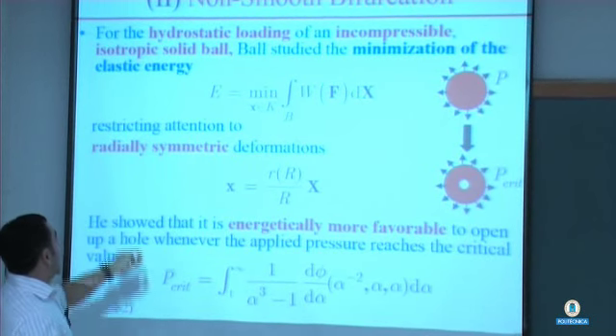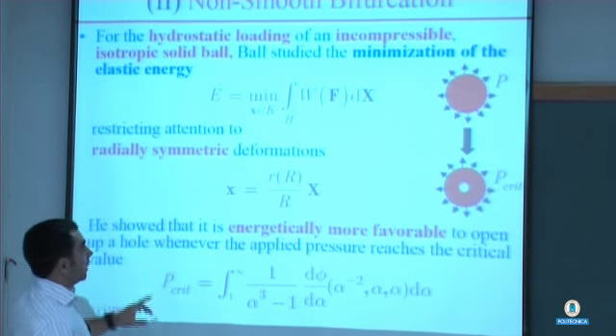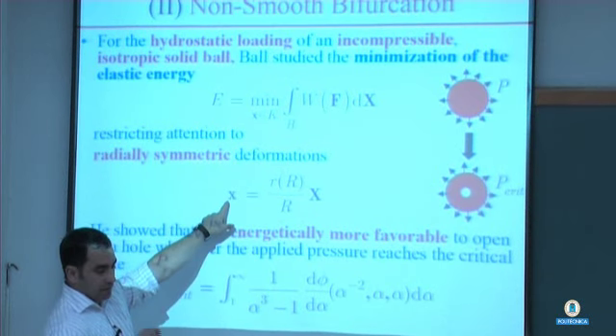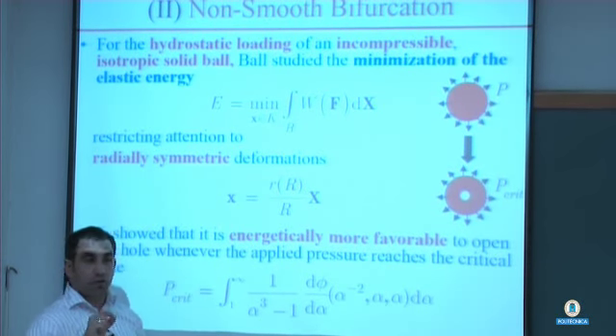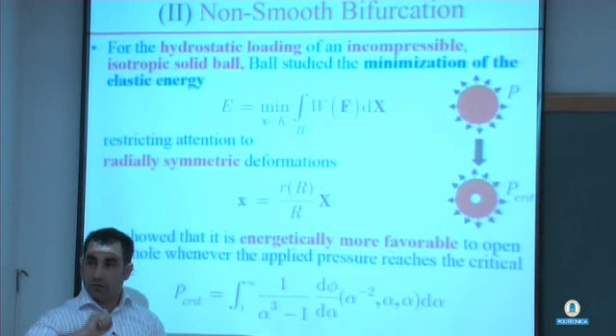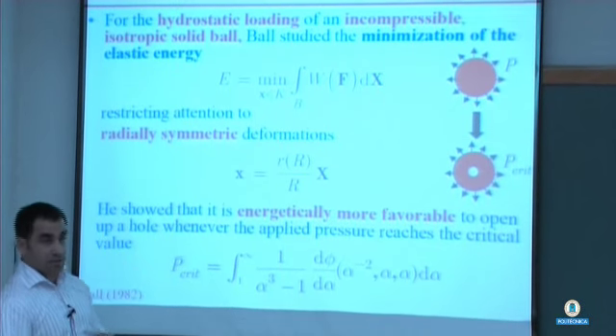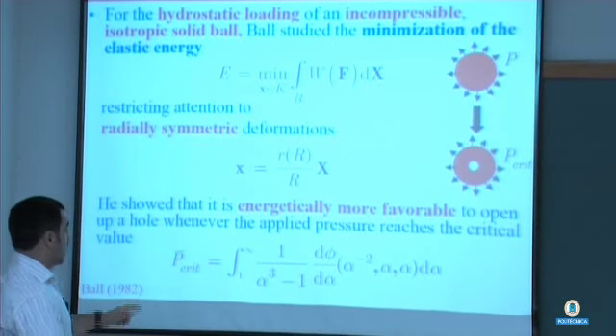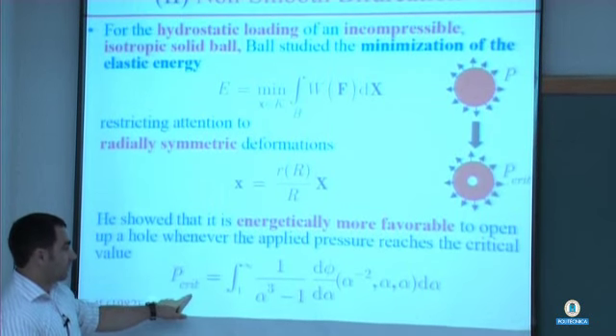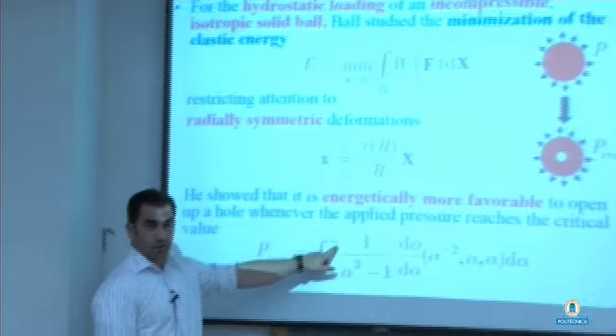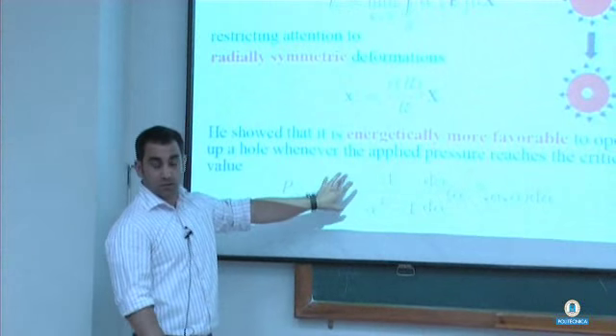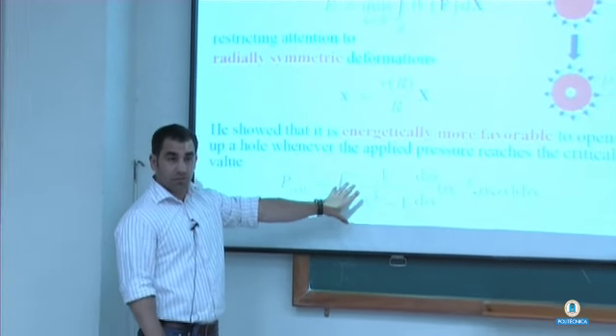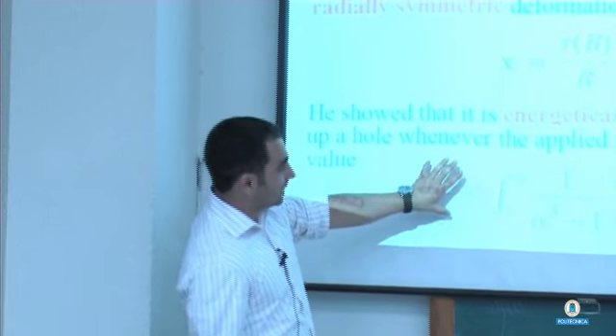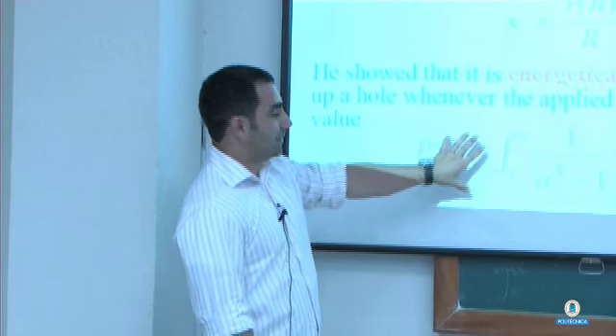And if you insist now on radially symmetric deformations and you allow the displacement field to not be continuous at one point, at the center, if you allow that, and you carry out the minimization, this is a non-smooth minimization, you get the same thing. You get the same formula here, right? Here is already F naught is 0, right? So this is what was done by Ball, and with rather nice mathematical methods, he obtained the same result as looking at the shell problem, right?